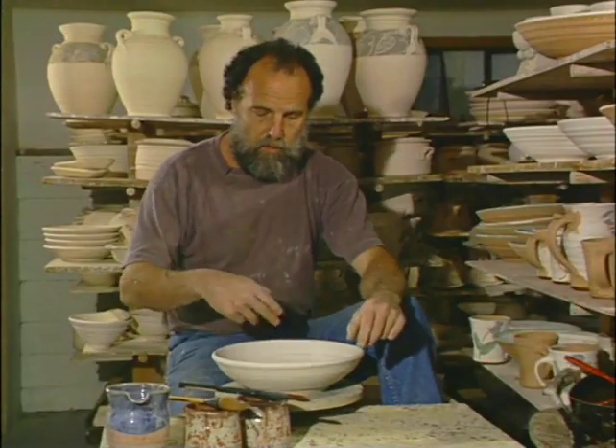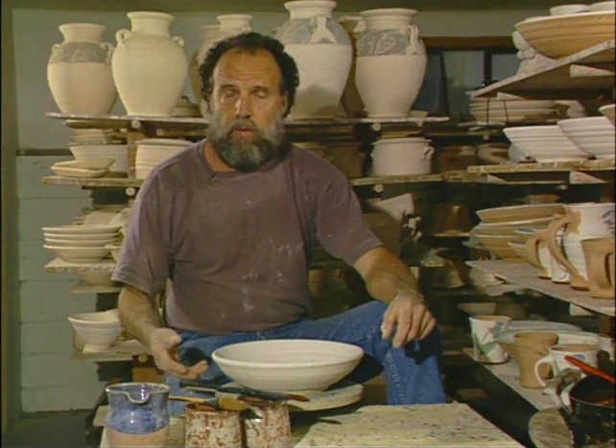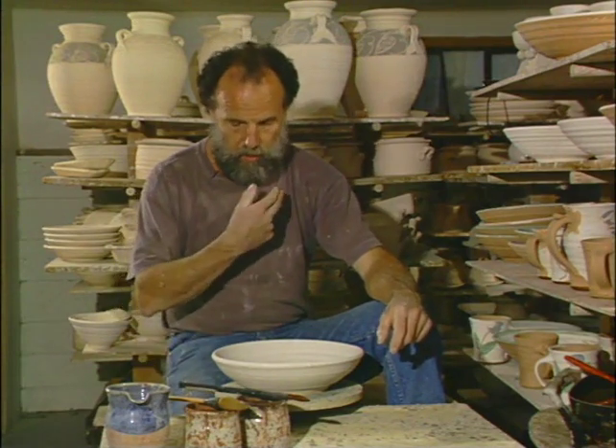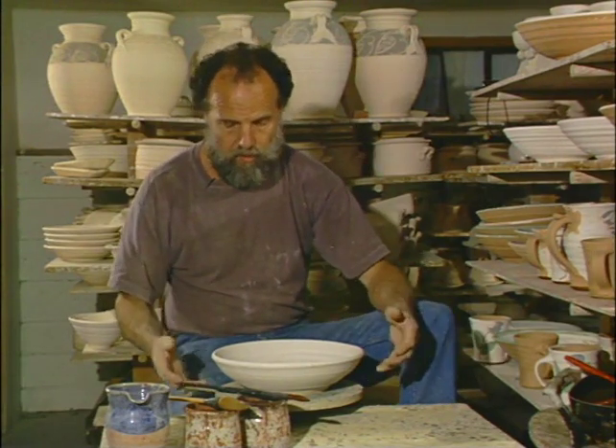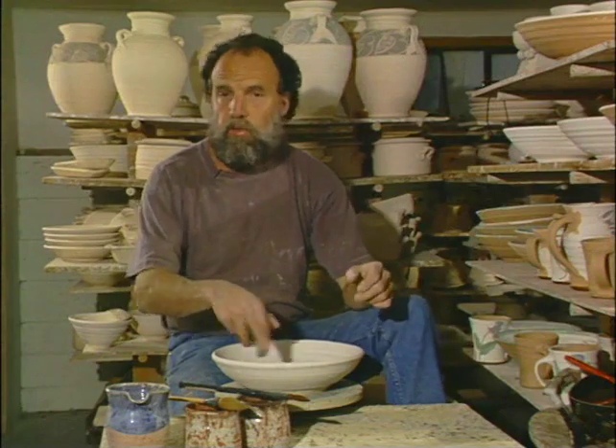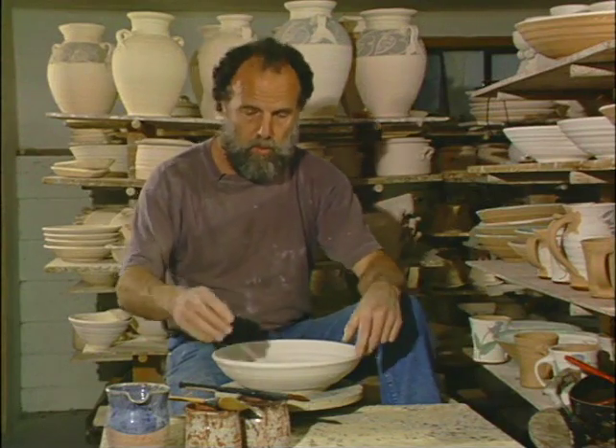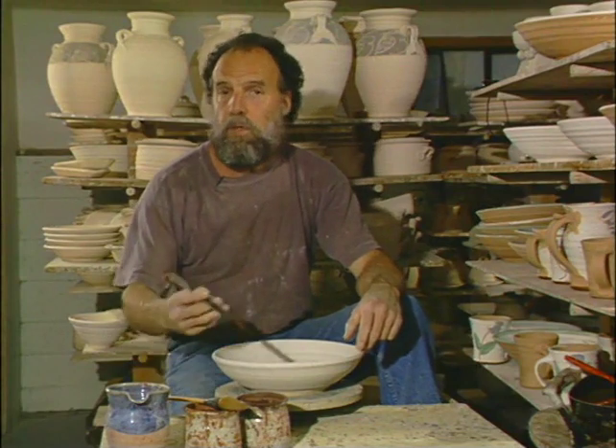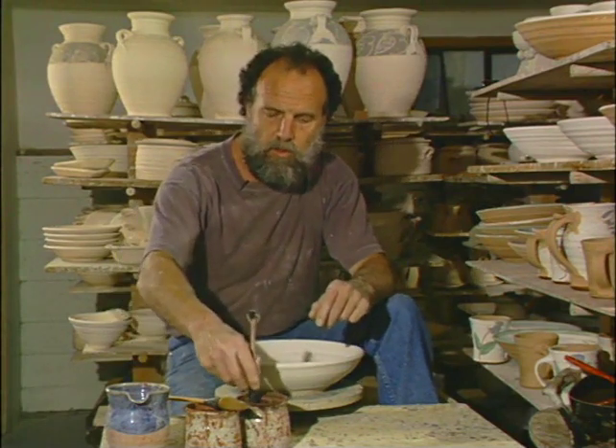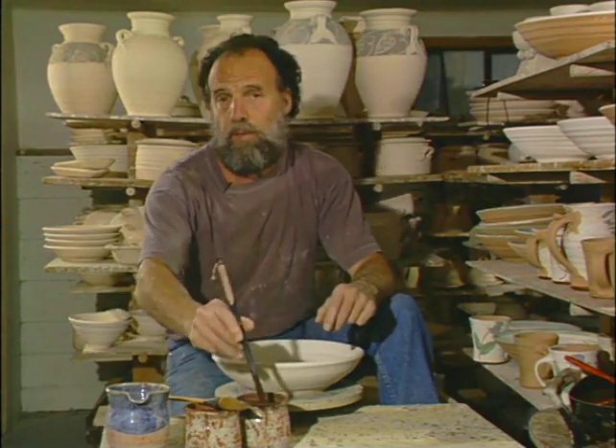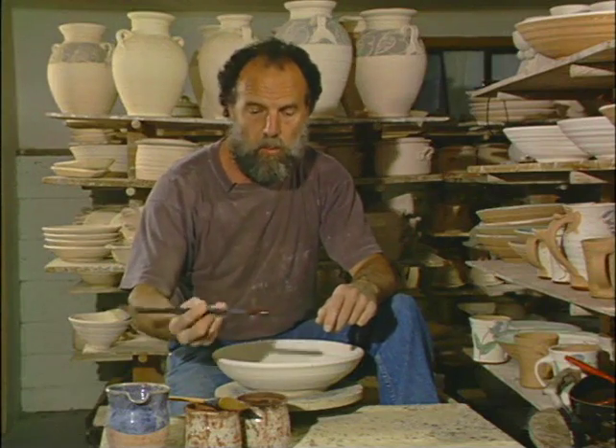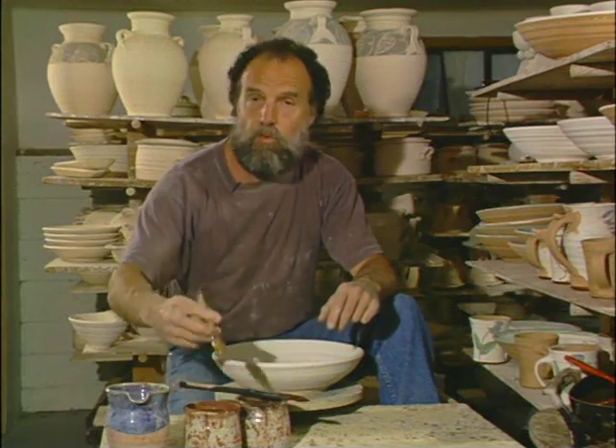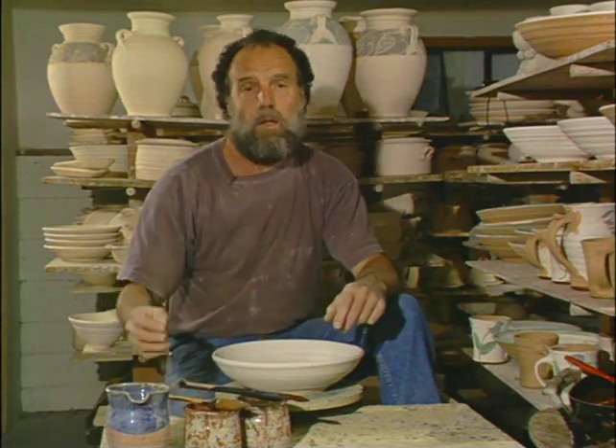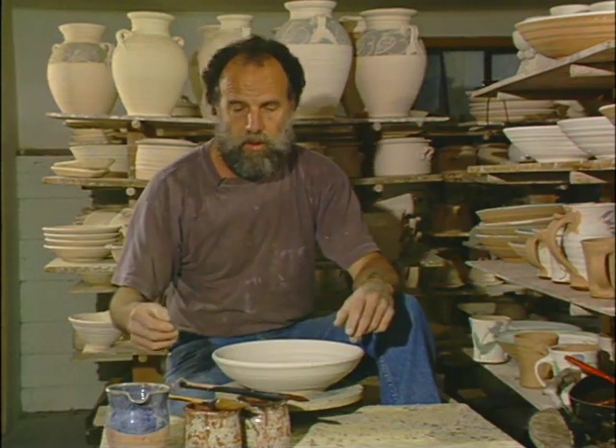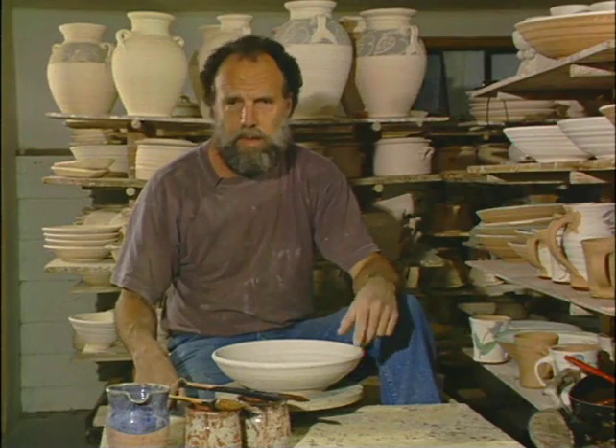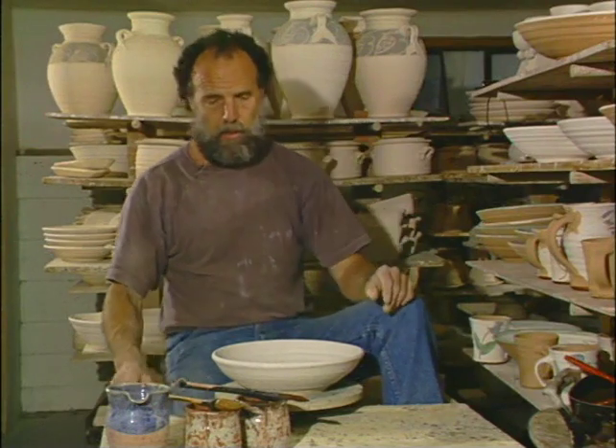We've taken some of the bowls that were undecorated and we've glazed them, glazed the bisque directly with glaze. And now we're going to do some overglaze decoration on the top. I'm going to use some paint brushes and some mineral oxide that has been suspended in water to the consistency of about a thick ink. This one is cobalt carbonate in water, and this one is red iron oxide. You can get a whole range of colouring oxides and commercial stains and overglazes from your ceramic supplier.